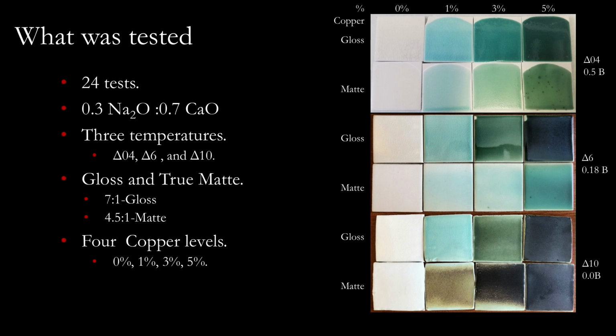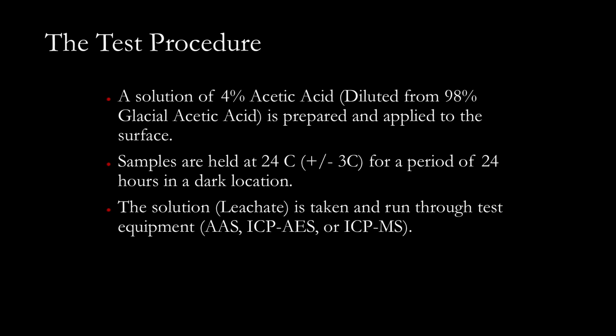One thing to note, there is not a bullet point on this, but the boron level does change based on the temperature we're firing to. As Sue pointed out, there's a level of approximately 0.15 needed for cone 6. For cone 04, we need approximately 0.5 moles of boron. So that was a factor in here.